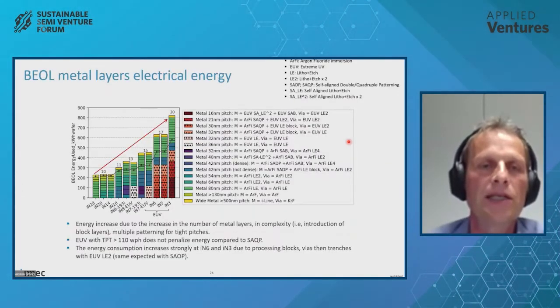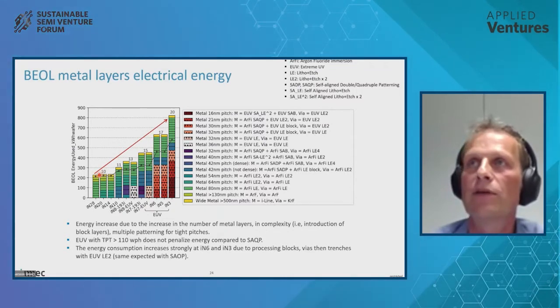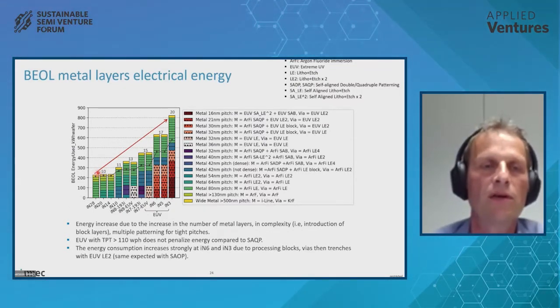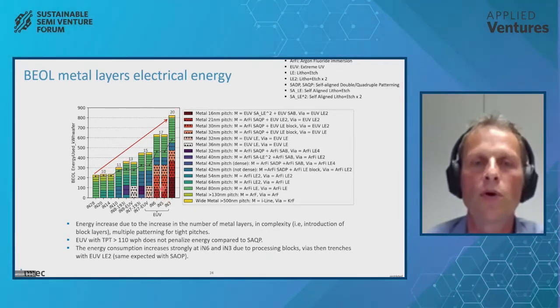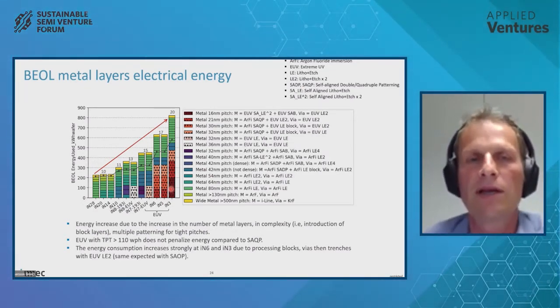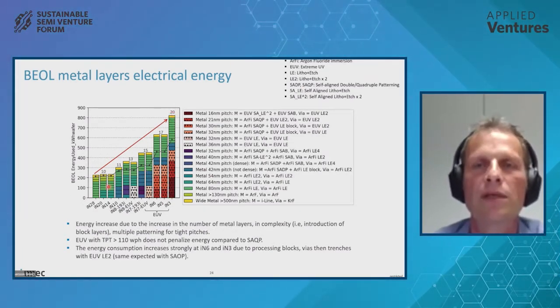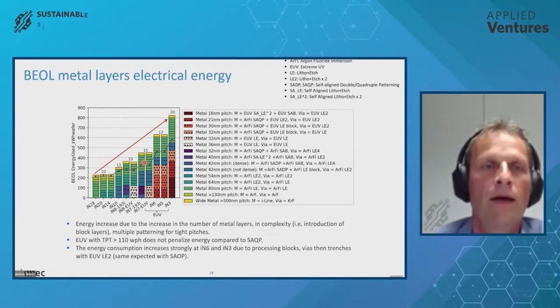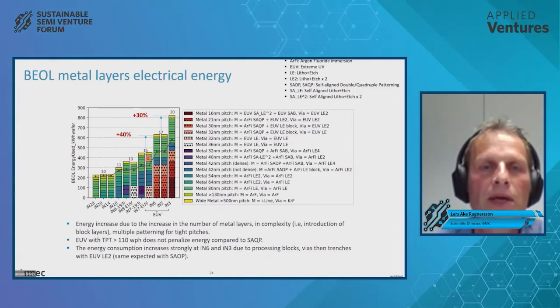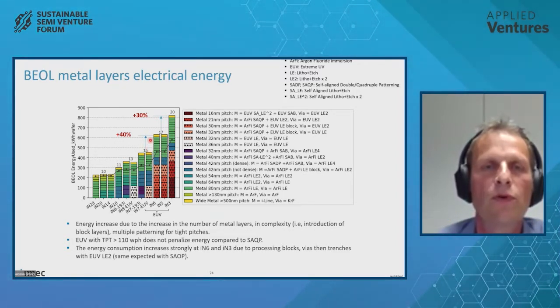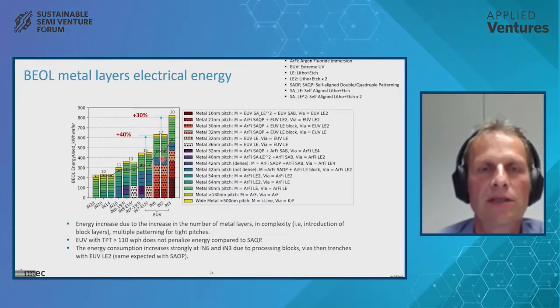Now the complexity is increasing quite a lot, if we look at the different devices, different technologies. So from 28 nanometer up to iN3, we see an increase in the number of back-end-of-line layers, and each of these layers is getting more and more energy costly to produce, and therefore our total energy use is increasing quite dramatically. So we see node to node, in some cases where we have to introduce very advanced block patterning, etc., increases in the order of 40 or 30%, which can be quite problematic.